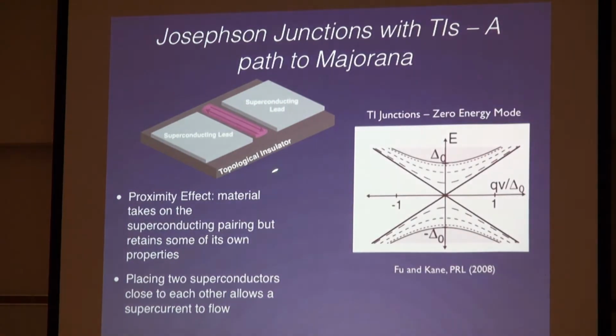But what they've shown is that, well, in this region where you induce superconductivity, you actually impose on the superconductor and the topological insulator this particle-hole symmetry. And because the topological insulator has a zero energy state when it's all by itself, that zero energy state stays pinned to zero once you apply the superconducting leads to it.